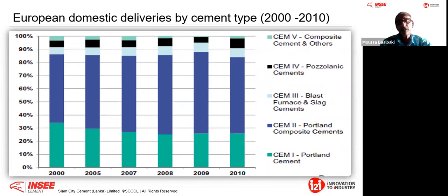What we did when we did a market discovery, we realized that less than 5% of OPC is remaining in Europe, and it is mainly used today for high-end precast, especially for some tunneling projects where demolding is after 4 hours. But with this type of solution, the cost per cubic meter of concrete can reach $300 to $350. This is niche. This is not general purpose, and it is not even something that can be considered because it is very niche. Therefore, if you look at the construction industry today, they are out of OPC. They are out of OPC.